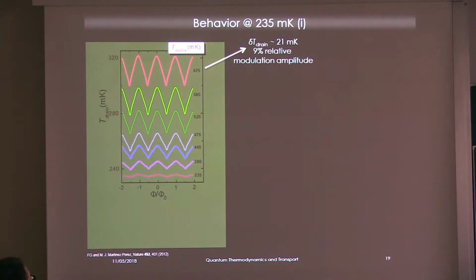So this is what we observed basically. You see that there are several traces at different levels of temperature in the normal metal drain. Here is the flux, here is the temperature in the drain. Okay, you see a nice oscillation of temperatures that show the periodicity, phi 0 periodicity, with the maximum for integral values and minimum for half integral values of the flux.